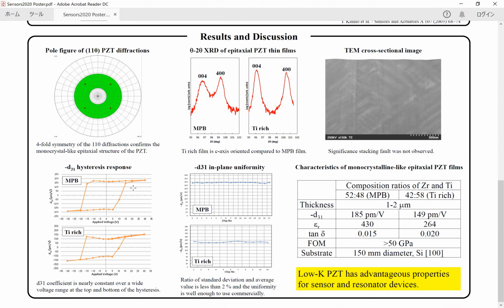Because of the ferroelectric nature of the PZT, hysteretic behavior of the transverse piezoelectric coefficient D31 is expected, and is shown here as a function of the applied electric field. For this plot, the applied voltage shown on the x-axis is the peak-to-peak voltage, and the DC bias voltage is half of the peak-to-peak voltage applied at each point.